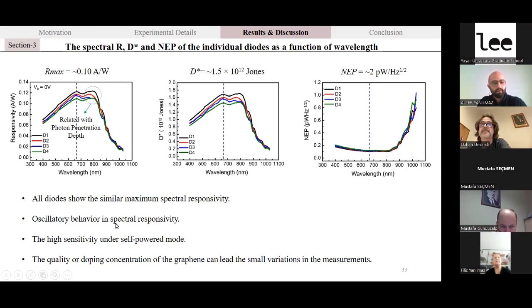All diodes, as I said, show a similar maximum responsivity. Oscillatory behavior in the spectral responsivity is also observed in this experiment due to the sandwich structure of the silicon-on-insulator, and high sensitivity under the self-powered mode is achieved. These small variations can be related to the quality or the doping concentration of the graphene in the measurement.